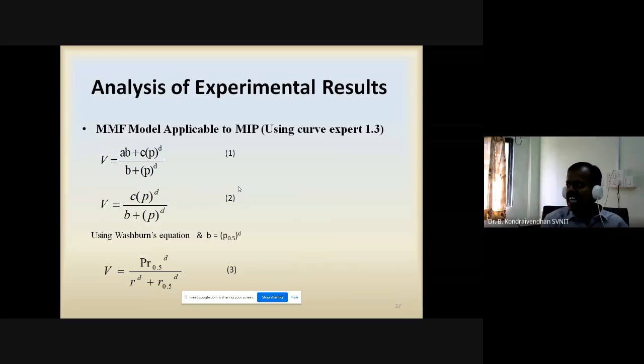What I was telling at the beginning, the pore distribution is governed by 3 parameters. That equation I got. So now I can say the pore distribution is governed by 3 parameters: one is permeable porosity P, R0.5 the mean distribution ratio, and the dispersion coefficient D. These 3 parameters you can easily calculate using your experimental data. Experimental work anybody can do. If you know the procedure, you can determine pore distribution parameters. You just have to understand how to perform the experiment.